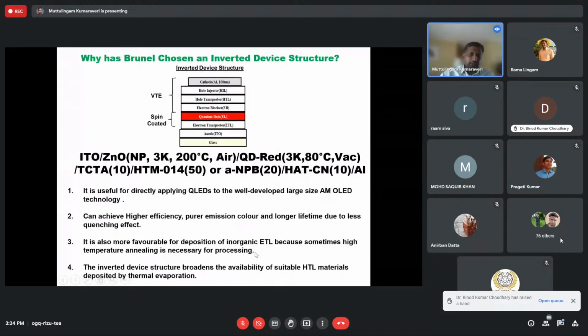And the ETL, normally we anneal at 200 degrees, high temperature. But here the quantum dot is on top of the ETL. If we put the ETL on top of the quantum dots and anneal at high temperature, the quantum dot will be affected, because the suppliers always tell us that 80 degrees is the maximum temperature we can anneal. Otherwise the characteristics of the quantum dots might lose their emitting sites. So here we can use a high temperature ETL, zinc oxide or metal-doped zinc oxide by the sol-gel method. We can use any temperature to anneal, because it's not going to affect anything on top of the ITO. ITO is never affected by high temperature.